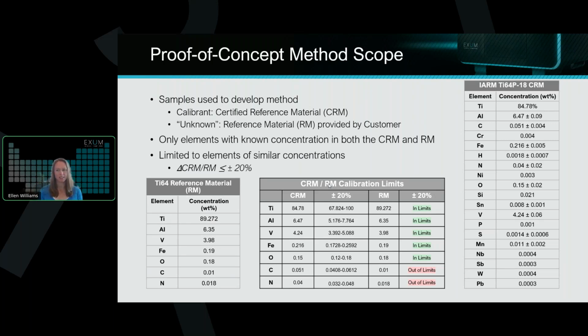It's also ideal that those elements are within a similar concentration, so plus or minus 20%. And so you can see in this particular case, the major elements, Ti, aluminum, vanadium, as well as a couple of minor elements, iron and oxygen, meet those criteria. So those are the elements that we included in this proof of concept method. Again, if we had more reference materials with closer values to those of the CRM, and with more elements quantified in them, we can expand this method scope.